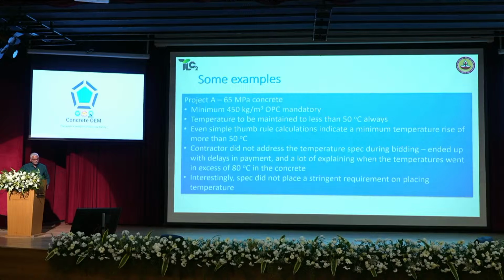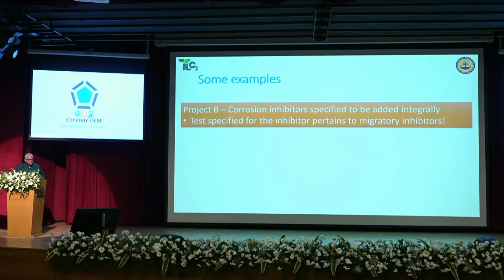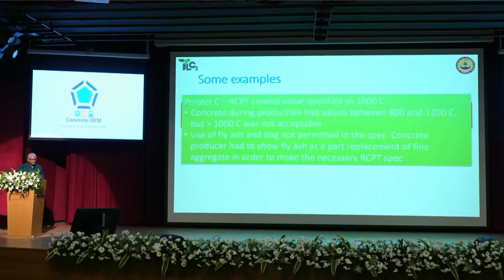And one more thing was the spec also did not place a stringent requirement on the placing temperature. They did not say that, okay, since we are asking you to keep the concrete so low in temperature inside, you should place at a very low temperature. They didn't say that. The second project, it's a simple issue. I've already talked about that. The corrosion inhibitors were specified to be added integrally, but the test specified for the inhibitor pertained to migratory corrosion inhibitors. So it really did not make sense that this test was there in the spec.